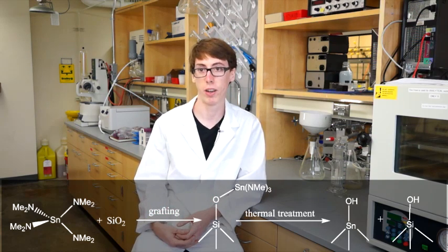We collected 32 scans and averaged them, at a resolution of 8 cm to the minus 1. We used air as a gas, and used a heating rate of 20 degrees C per minute. We heated the sample from room temperature to 550 degrees C.